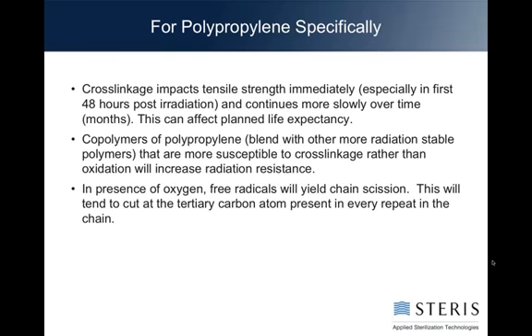Copolymers of polypropylene will frequently be labeled as a copolymer on your specification sheets. What they really are is a blend of polypropylene with other more radiation stable polymers, things that are known to have a tendency to cross-link. In general, a product that cross-links will be more stable to radiation than one that predominantly will go through scission, because there's a limit to how much cross-linkage it can do. So if you blend in polypropylene with something more resistant than it is, for example, frequently the additive would be polyethylenes, those types of materials together will be better than either one separately. The addition of the more stabilizing plastic will increase the tolerance of the polypropylene, correcting many of the known problems that will occur with it.